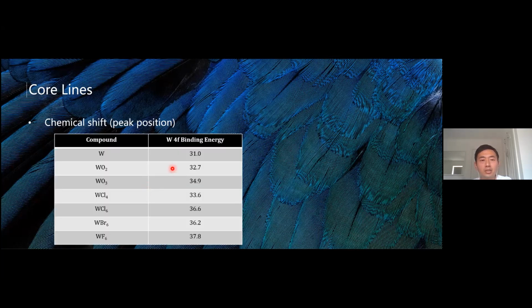For example, in this table, we could see that tungsten 4+ is more oxidized, therefore it has higher binding energy than tungsten metal. And the 6+ has higher binding energy than 4+.